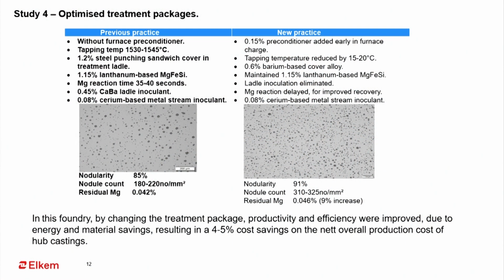Changing from steel punching to this conditioner will help to reduce the tapping temperature by at least 15 to 20 degrees. By reducing this 15 to 20 degrees, there are two side effects. One is, if you increase the melting or tapping temperature, it will definitely deteriorate the quality of the metal. But reducing this 15 to 20 degrees will help to minimize the deterioration of the metal quality. And another is power saving. So in both cases there will be savings, and finally you will get a better structure.